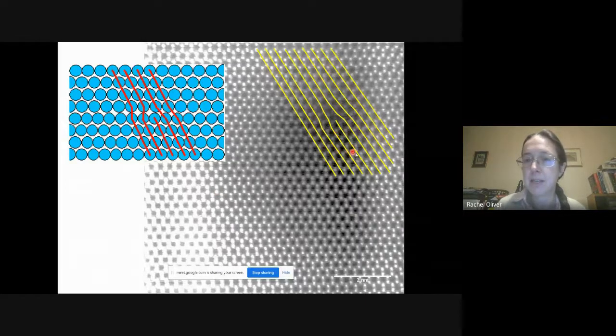And we can see that just like in my schematic, there is this missing half plane of atoms, and the other atomic planes deviate around that. And in this region here, where we have the dislocation core, we have the missing half plane running into the page through the crystal, away from us as we look at it. And that is exactly the same kind of defect we talked about in the copper.